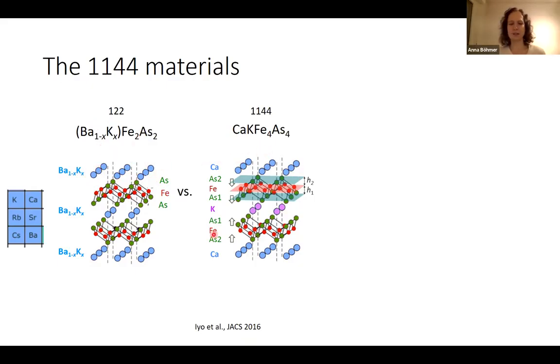We have a doped 122 compound. On the other hand, and that was the discovery in 2016, some of these elements don't mix. When there's a size mismatch, they separate in layers. So we have alternating, say, calcium, potassium layers as one example. This is not an alloy. This is really a 1144 compound.